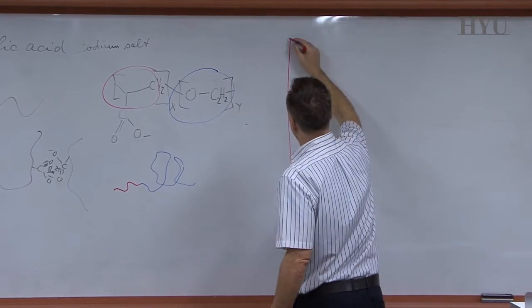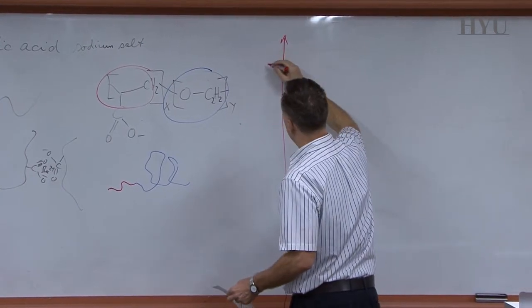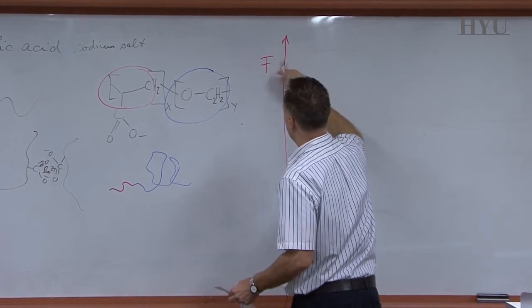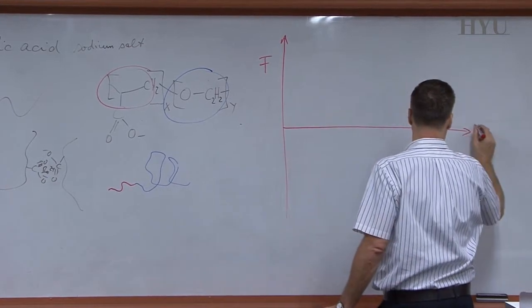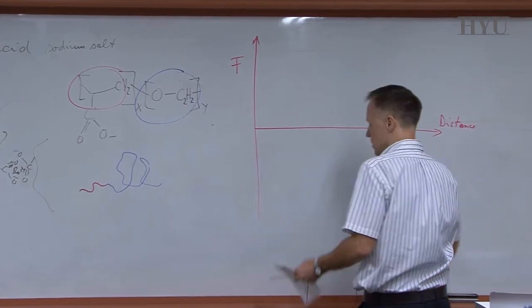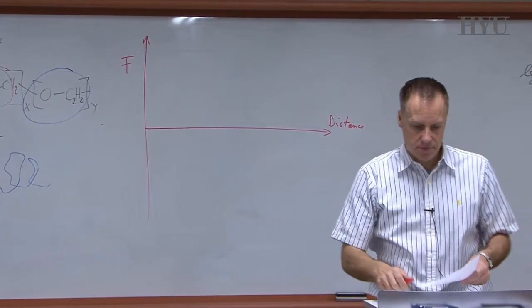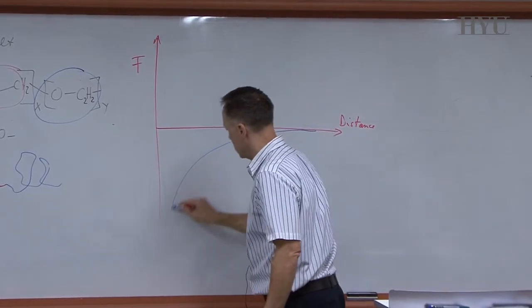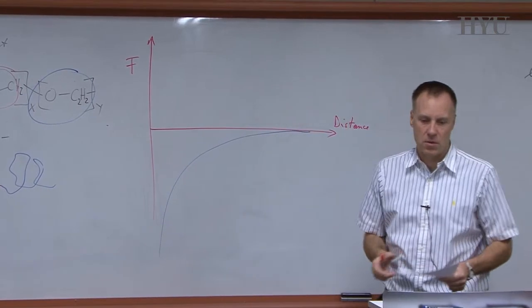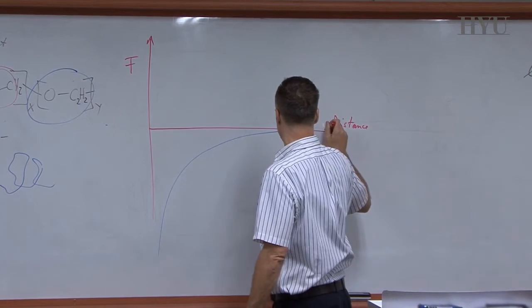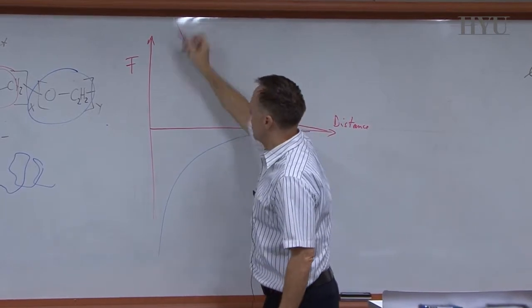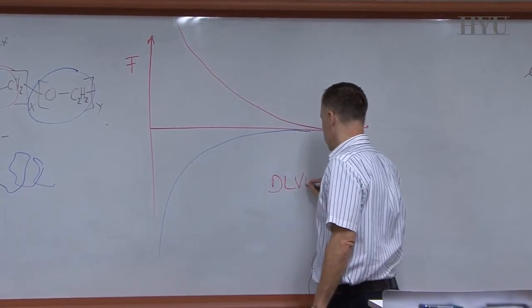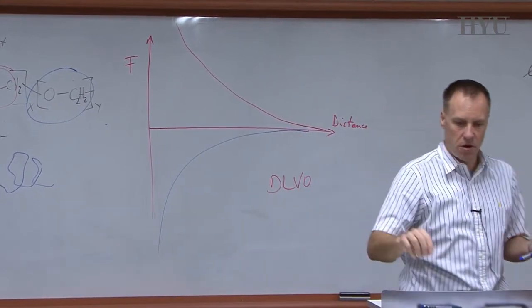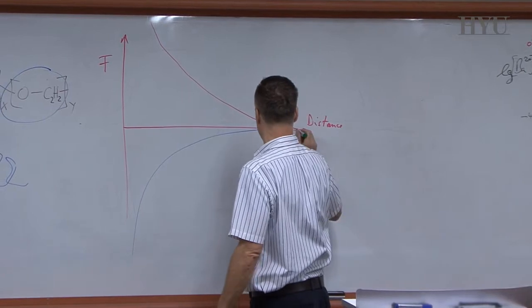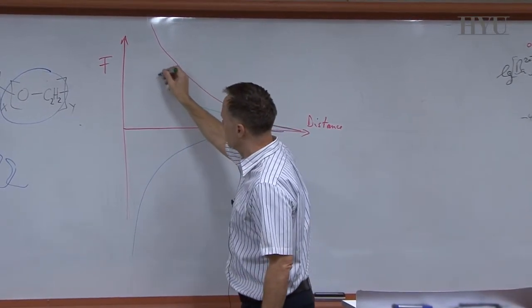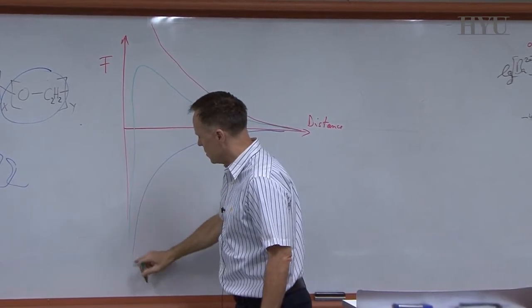Now again here, the potential or force, it doesn't matter. Let's plot the force right now. The force in between two surfaces against distance between the particles. So we know generally we have, of course, this van der Waals attraction. A curve like this typically. And then we have, earlier, electric double layer repulsion. And depending on the size of the electric double layer repulsion, it could be running like this, for example. Yeah? And then in the so-called DLVO theory that we had, we add these up, and then you get your joint curve. And that would be, for example, a curve that looks like this, going up here. And then at some point, this is larger and dominates compared to this.